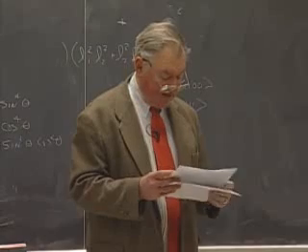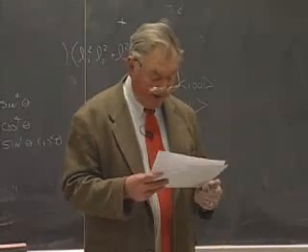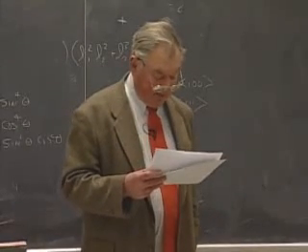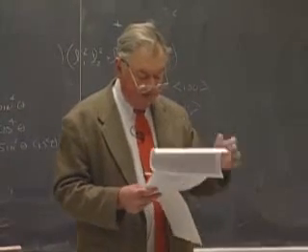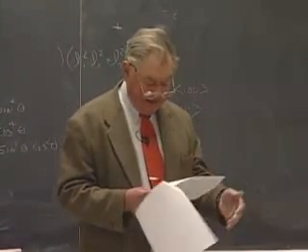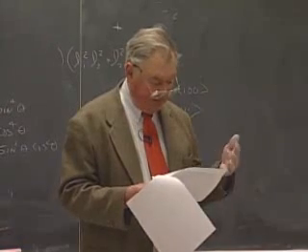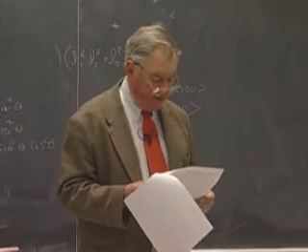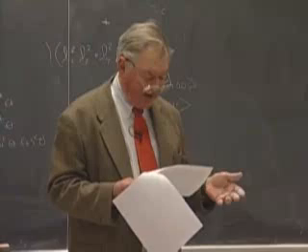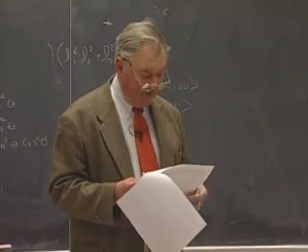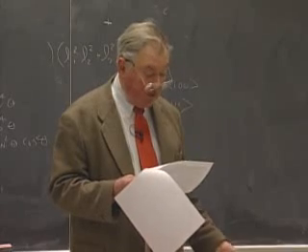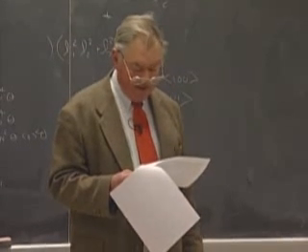The two different sets of data here are for measurements by two separate observers. The second page is for aluminum oxide. And again, you see the order of magnitude of the numbers is on the order of 10 to the 12 dynes per centimeter squared in general, and variation from one to another for aluminum oxide of a factor of about 4.